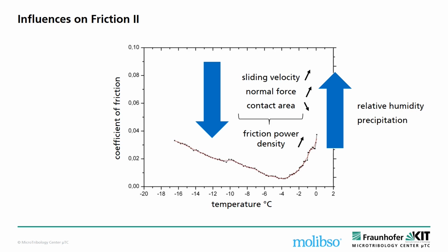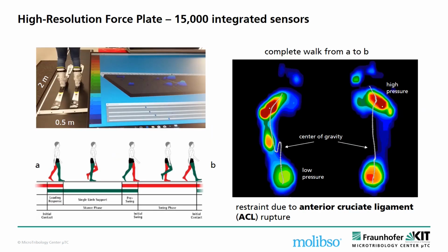And as a tribologist, one always has to think in terms of energy and energy dissipation, and this energy goes into the increase of temperature of the snow, thereby increasing the water film thickness, and this means we have a better lubrication situation and the curve goes down. The other way is possible as well: when either snow or air humidity or both are high, the curve shifts to higher values. When there is precipitation in the form of fog or rain or snow, we increase the curve as well.